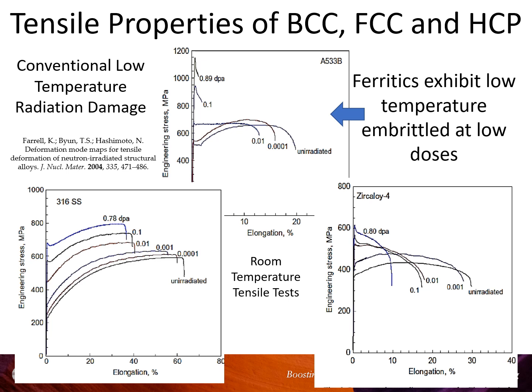So how does this load drop phenomenon, which is pretty common in all metals, compare between austenitic steels and ferritic steels? Here are ferritic steels, austenitic steels, and zircaloy. You can see the effect of irradiation, going from an unirradiated material to the irradiated material, is that in the austenitic steel and the zircaloy, you get this load drop, and that's related to the channeling.